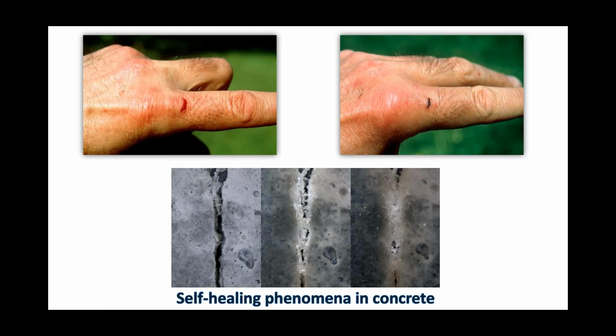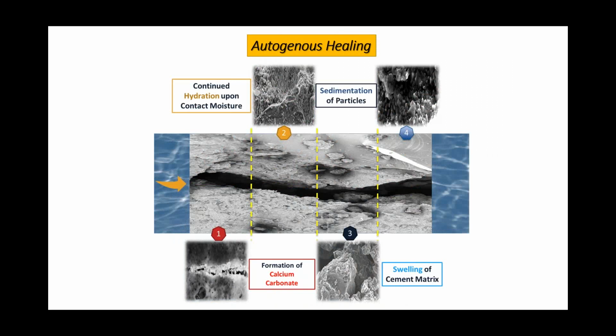cut in your finger heals, and that typically happens inside the concrete. So one is formation of calcium carbonate when the water is present. And also the continuous hydration of the concrete, which acts as a barrier, and also swelling of the cement matrix. So all four mechanisms are responsible for the healing or sealing process inside the concrete. But there is an issue. You can't rely on this natural phenomenon because sometimes it might not happen, or it's limited to certain crack widths, less than 0.2 millimeter, which is not a lot compared to other types of cracks that I mentioned.